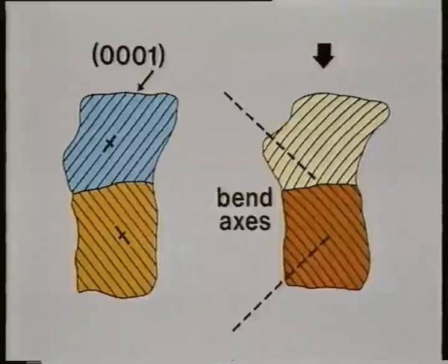The buckling always occurs after glide or shear has been initiated parallel to the basal plane and is associated with the development of undulose extinction. The position of the bend axis within an individual grain will depend on the constraint exerted by the neighbouring grains, which are also undergoing geometrical changes as a result of the deformation.